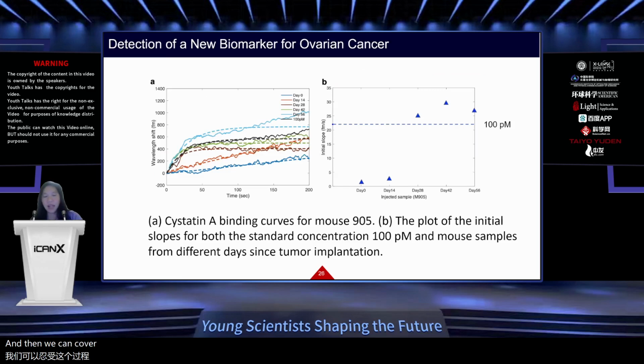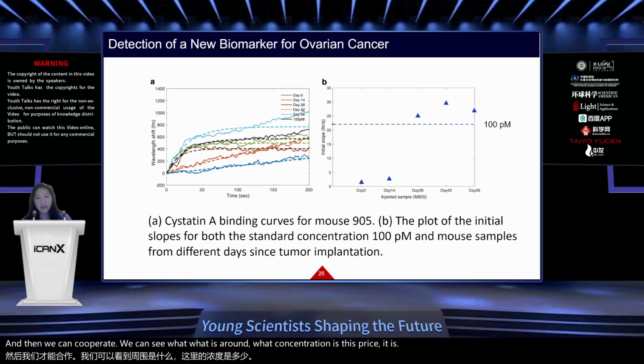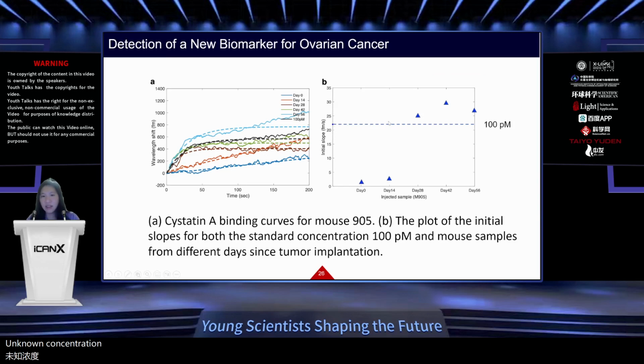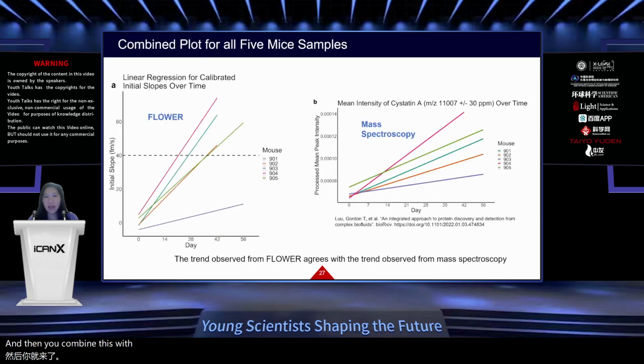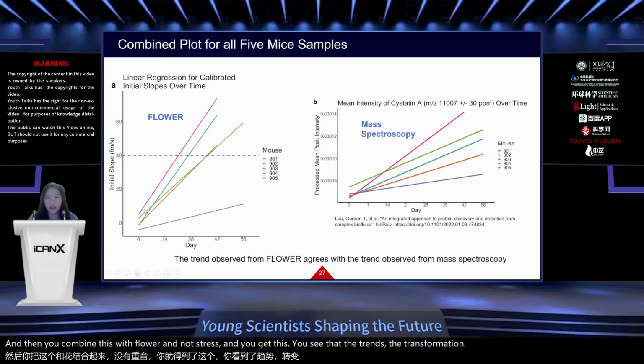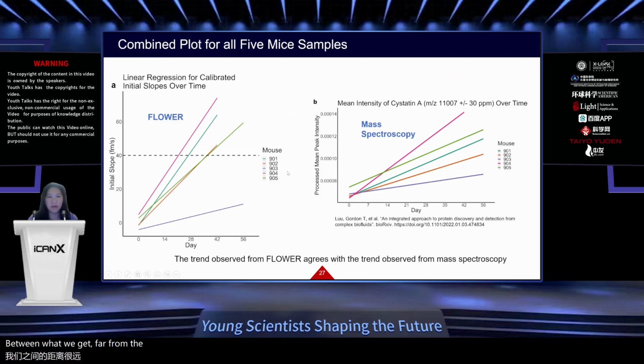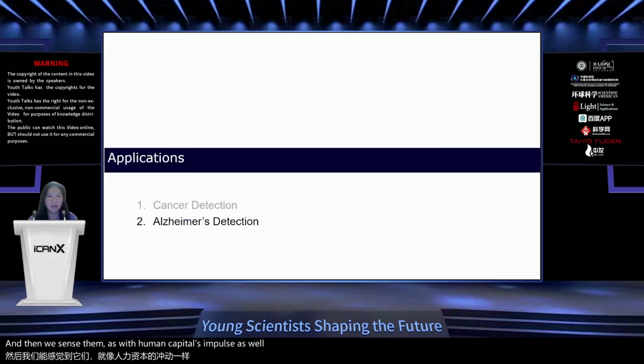And then we can calibrate and see what concentration this is present at in the mice. So in this case, the student injected a known concentration into her sample and saw this dashed horizontal line is around 100 picomolar. And then you combine this with fluorescence and mass spec, and you get this. You see that the trends correlate between what we get from fluorescence from 5 different mice and what they get with mass spectroscopy. And then we've since done this with human tampon samples as well, though I don't have that data right here in these slides.